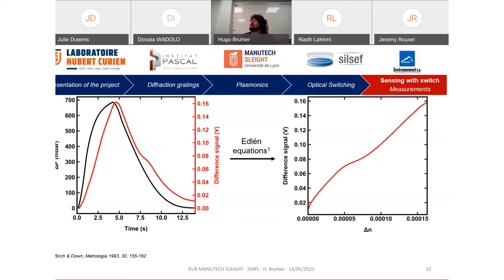and we make a linear regression to have the sensitivity of our sensor, which gives us a sensitivity of 866 volts per refractive index unit with a correlation coefficient of 0.987, which is not perfect, but nearly good for first measurements. And we compute a limit of detection lower than 10⁻⁵ in the change of refractive index.